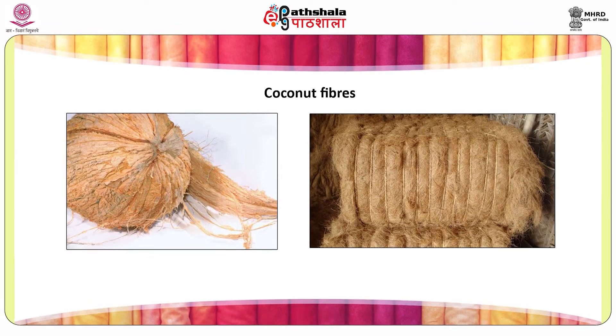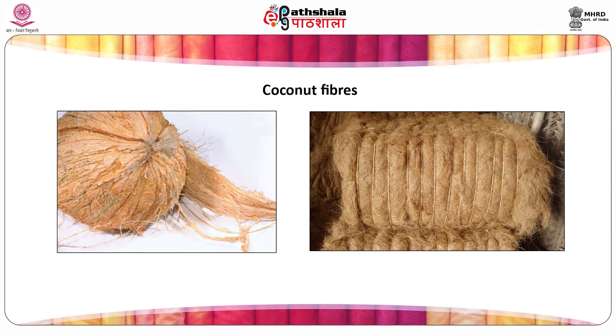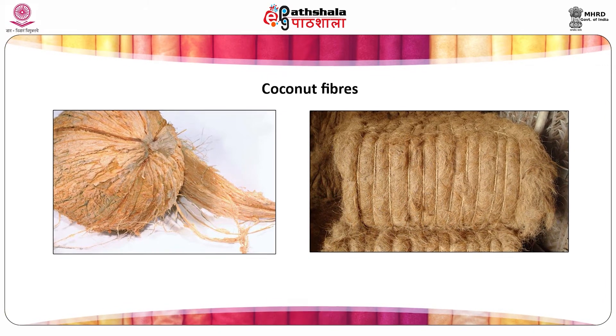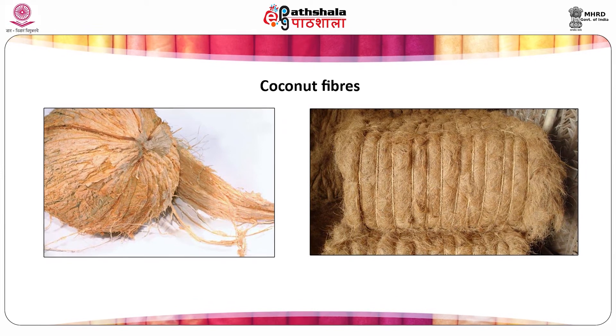The second fiber is fruit fiber: coir. Coconut fibers are extracted from the outer shell of a coconut fruit. It is called coir fiber, which is coarser, thicker and a durable fiber used for preparing many items from rope to floor mats. The fiber contains 46% lignin and 44% cellulose. Higher lignin composition makes the fiber stiffer. The fibers are extracted from both matured and immature coconuts, and the quality of fiber depends upon their maturity. Brown fibers are from matured coconuts, which are thick, strong and have high abrasion resistance.